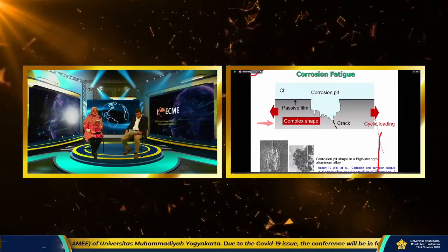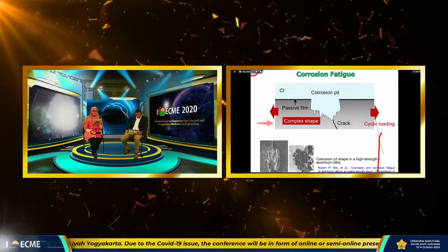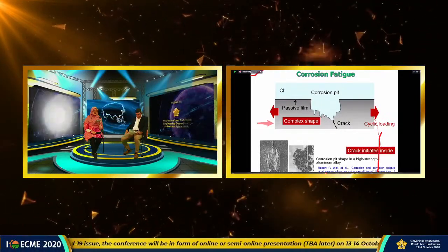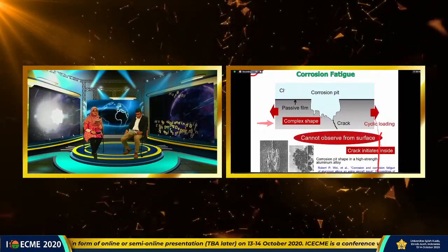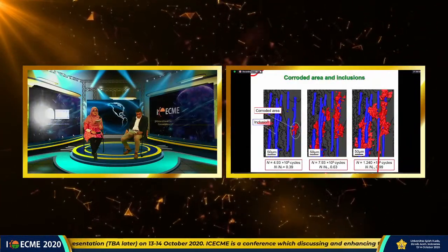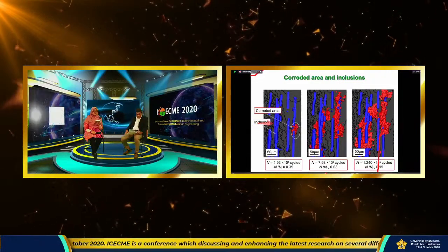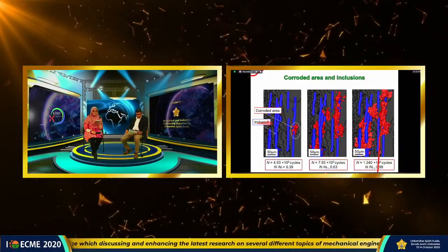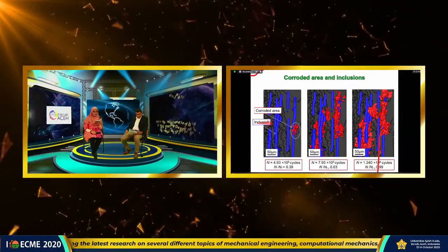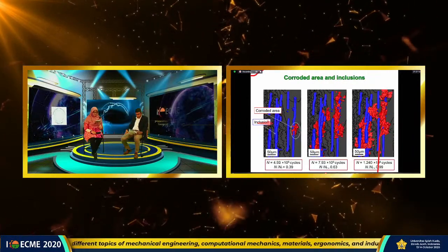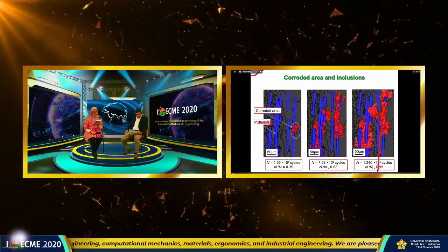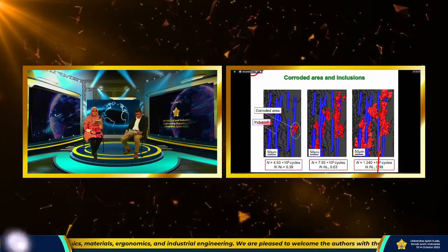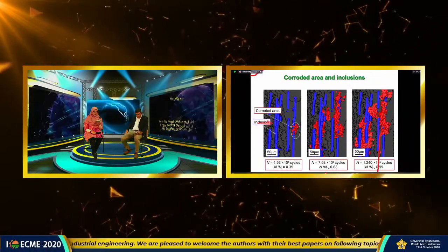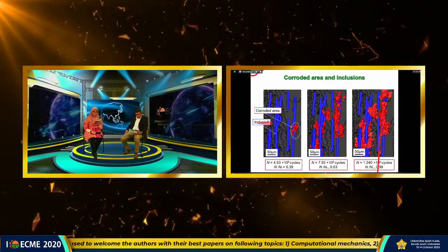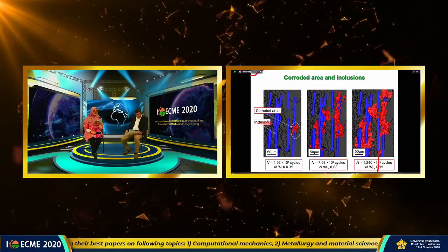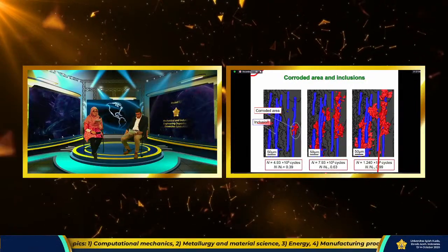So we observed the change of shape during corrosion fatigue. These are the CT images. The blue region shows inclusion, and the red regions are corroded area. You can see the extension of corroded area around the inclusion with the number of cycles. This one shows the number of cycles. So the corroded area extended like this. This phenomenon occurs under the surface, so you cannot observe it from the surface.